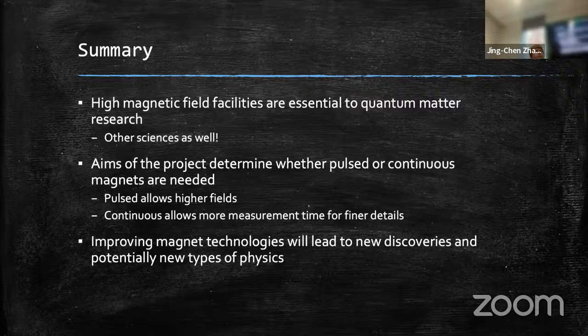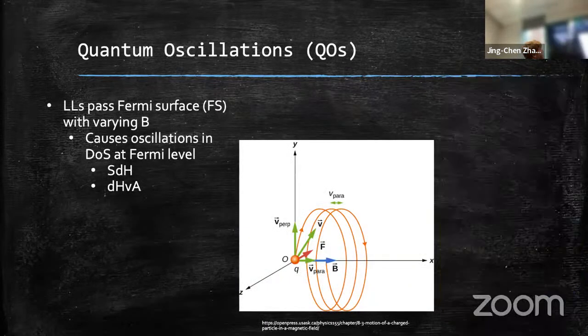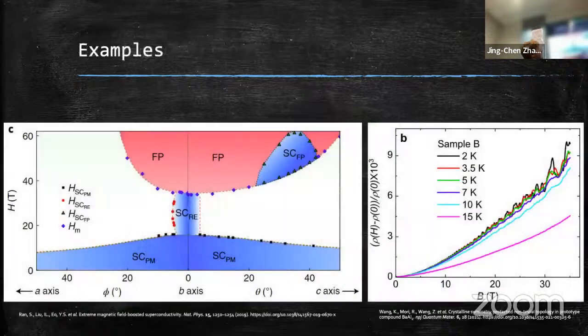With regards to temperature dependence, usually a lot of these quantum effects start becoming more and more important at lower temperatures, when you screen out your phonons, you screen out more dominating temperature scales. But for an example, I was showing quantum oscillations here, in the samples I just measured. So this is in resistivity, right? As you can see here at 15 Kelvin, the oscillations are gone. In my samples, I could still see oscillations at 50 Kelvin, which is a huge temperature scale, normal for experiments.